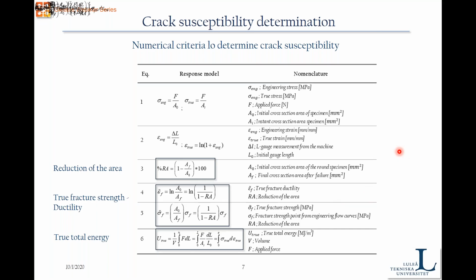After obtaining the results from the thermomechanical tests, we applied different numerical criteria to determine the crack susceptibility, as you can see in this table. The first equations are just to plot the flow curves, which are very well known, the stress-strain, engineering and true. But for the crack susceptibility determination, we were using a combination of 3 different criteria. The well-known reduction of area, which we believe is the most common, but it can also overestimate some of the results.